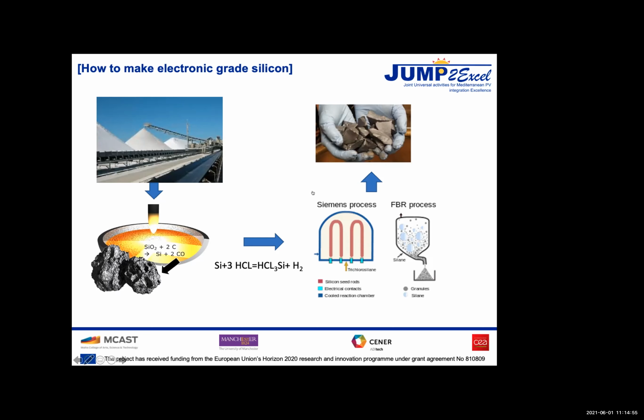We smelt it with carbon to produce lumps of what we call metallurgical grade silicon. That's a high energy process, obviously. And then we react it with chlorine to refine it further. That's called the Siemens process. That's also a high temperature process and uses chlorine, which isn't a terribly nice compound or element. But at the end of the day, we end up with the thing shown at the top here, which we call feedstock, which is relatively pure silicon, which we can use to make our solar cells.